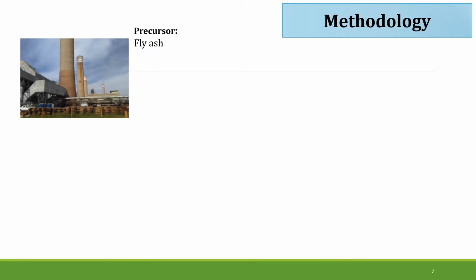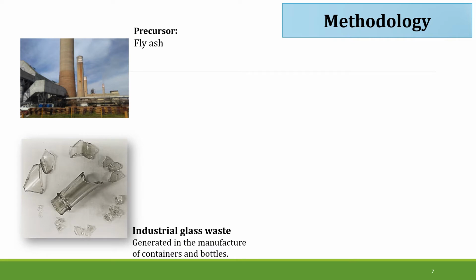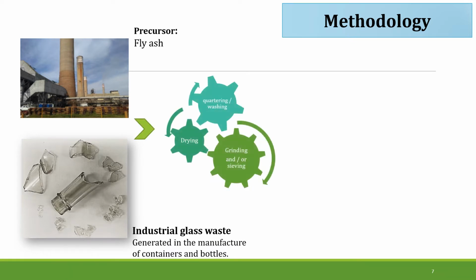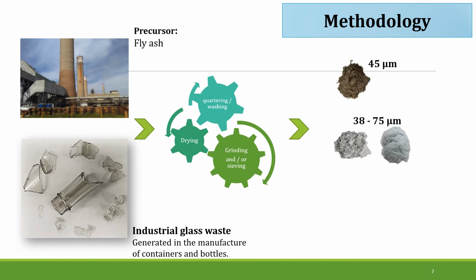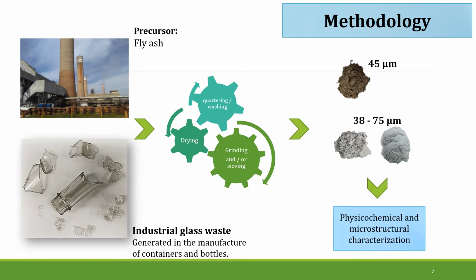The methodology used throughout this research can be divided into two stages. The first stage is obtaining and conditioning the raw material. In it, the fly ash was obtained from the Federal Electricity Commission thermoelectric plant, while the glass waste came from the Pavisa Group. The materials went through a process of washing, in the case of glass, and quartering, in the case of ashes. Later, both were dried, ground and sieved to obtain particle sizes of 45 microns in the fly ash and 38 to 75 microns in the glass residues. Finally, a physicochemical and microstructural characterization was carried out.